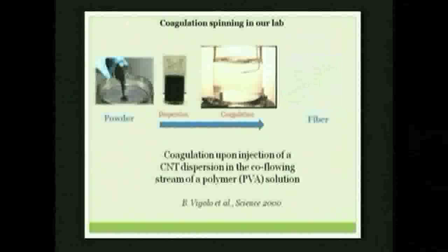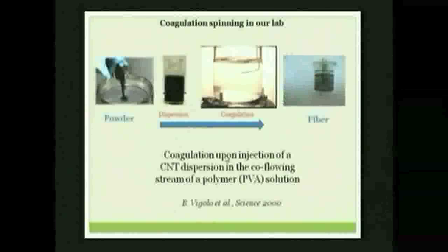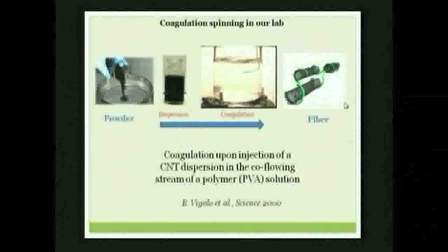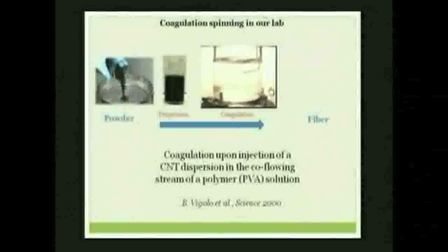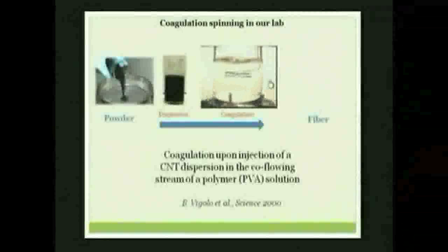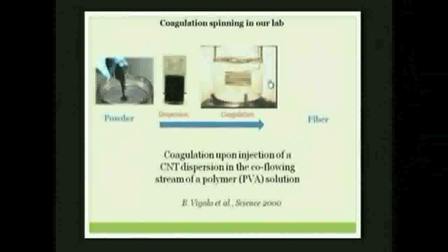Then we take this dispersion and we inject it using this syringe that you see into the coagulating bath. In this bath, what do we have? We have water and a coagulating polymer. This is polyvinyl alcohol. What happens when we do that? This is a video, so I have to start it. Okay. So when you inject a dispersion inside this coagulating media, you observe the spontaneous formation of a fiber, as you can see here.